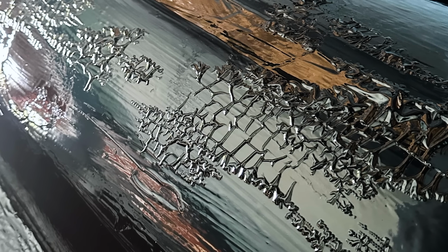Unlike with epoxy gel coats, vinyl esters really can't be left too long, so if you're at all unsure, then simply wait a few more hours. In fact, even days later, you're still going to get excellent adhesion between coats. If you don't leave enough time for it to cure, then there is the very real risk that the next application is going to soften and attack the first, leading to a wrinkling effect, often referred to as alligator skin.